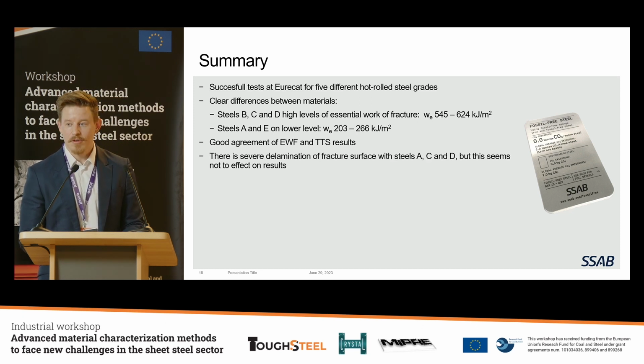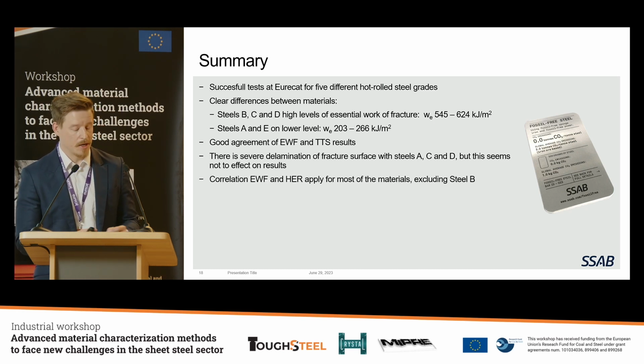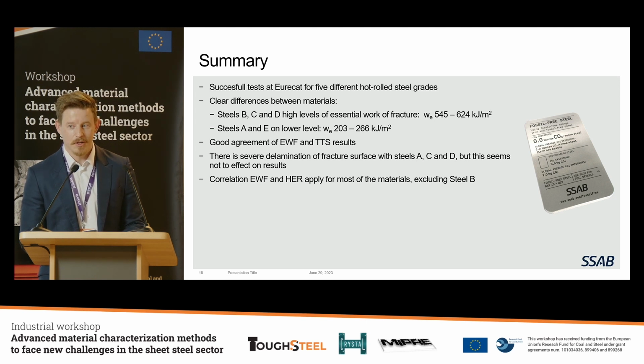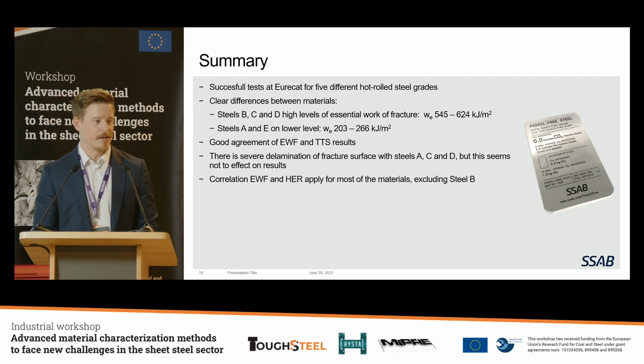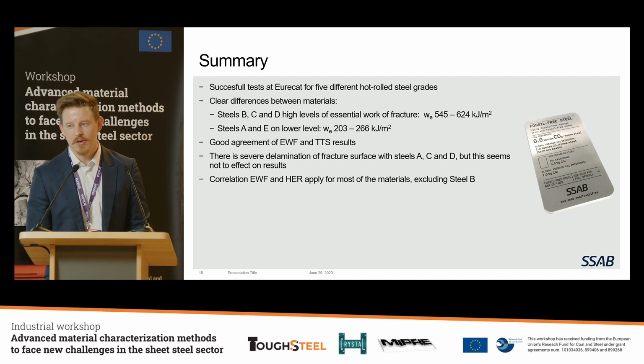And we found out that the ferritic grades are showing delamination, but it's not actually affecting that much on these results because steel A is on a low level and the other two are on a very high level with the delamination. And also we've tried, of course, the previously published correlation from Mr. Frómeta, that is the hole expansion ratio and essential work of fracture are really correlating. And we could say that, yes, there is a correlation, but there is the one material that is not behaving. Let's say there is something going on, and we have to look at that more closely.